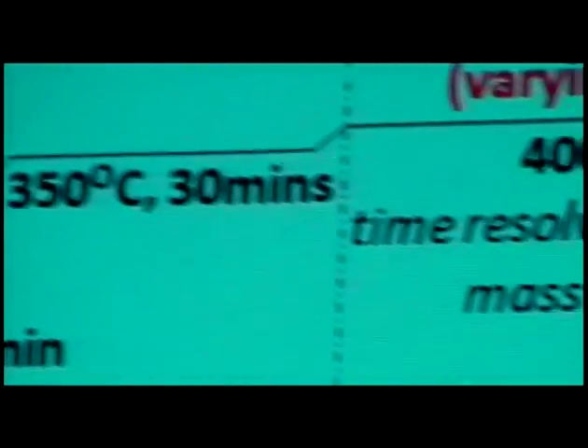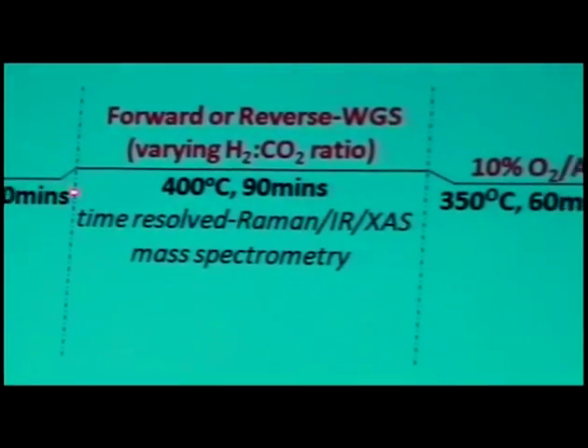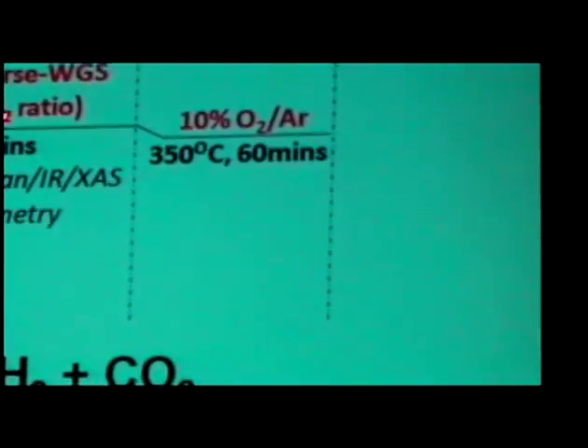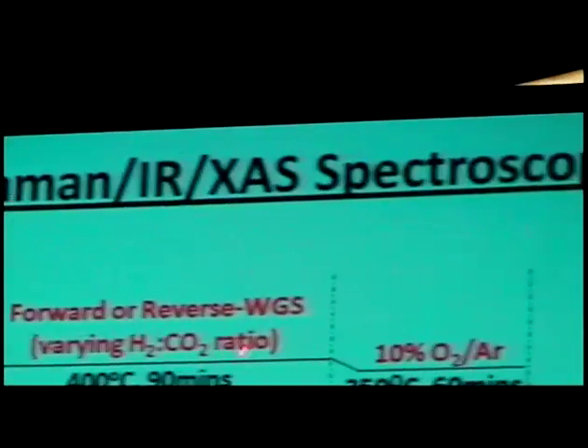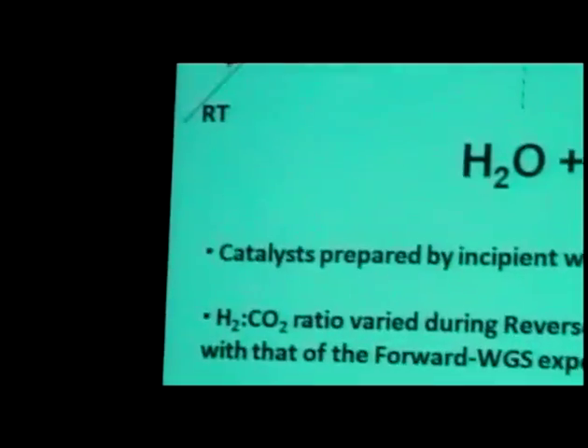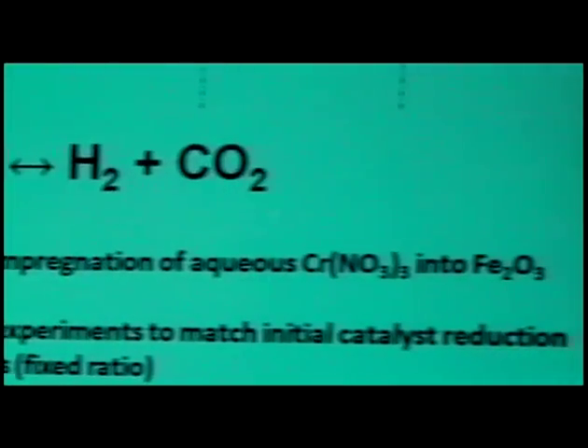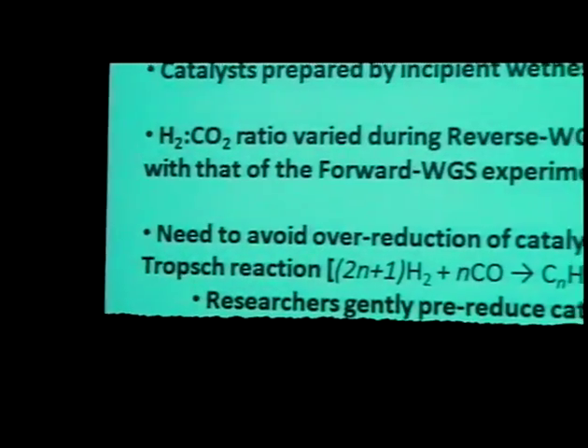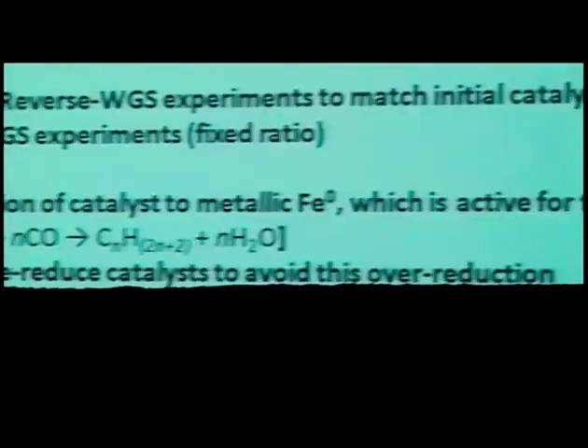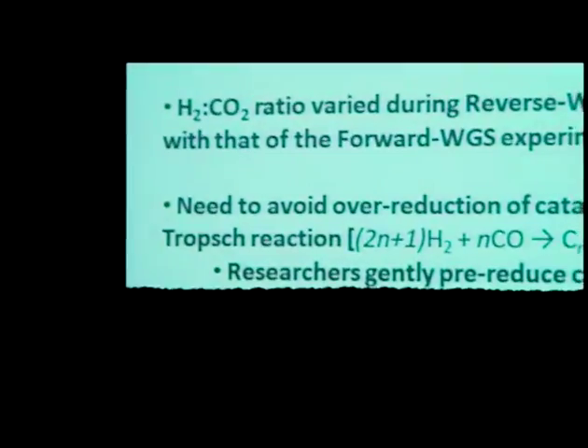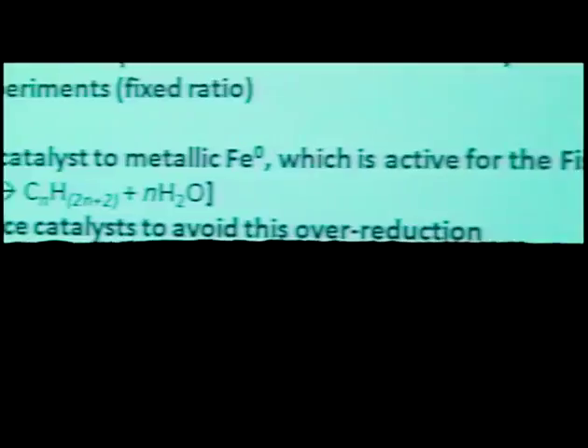And basically this shows you how we treated the catalyst. We first heated them up in air and oxygen to 350 C, and then we exposed them to the different conditions. We did both reverse water gas shift and water gas shift. The reactions are in equilibrium, so at the end of the day, you get the same steady state results. And then we also cooled it back down slightly and oxidized it to see how, you'll see some things are reducing. We wanted to see what is reoxidizing, and we found it to be very informative when that happens.